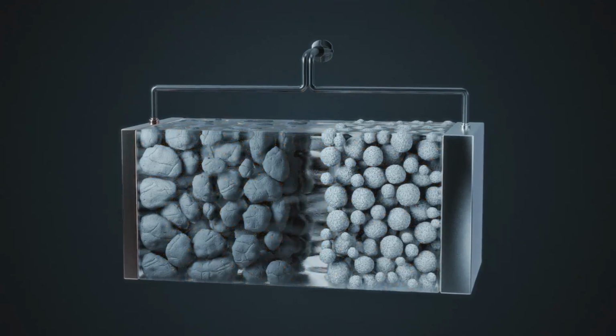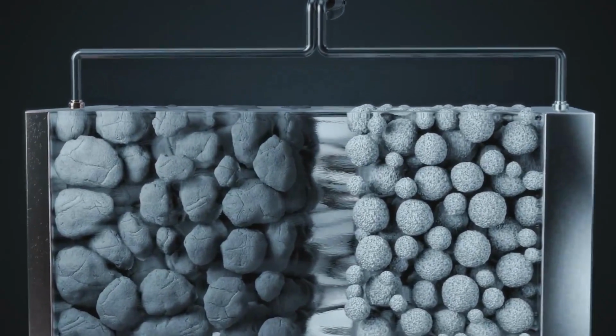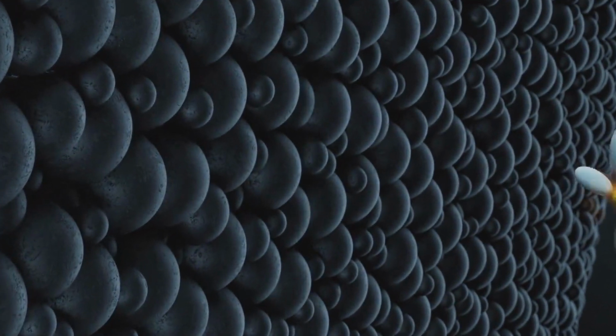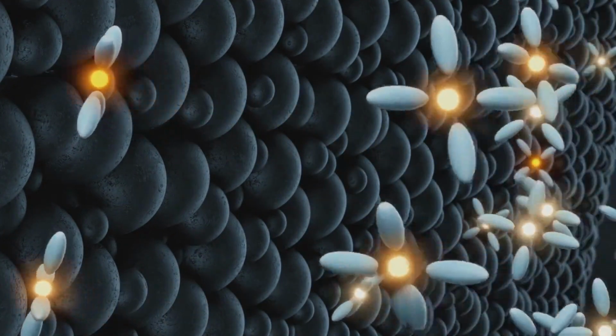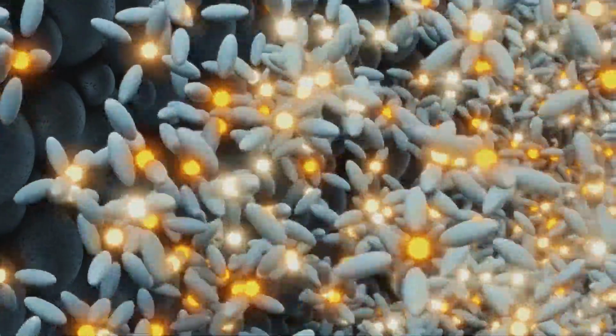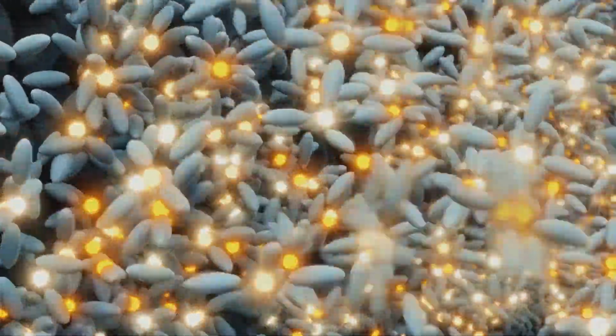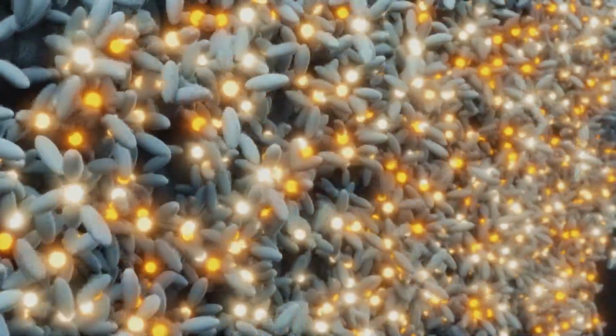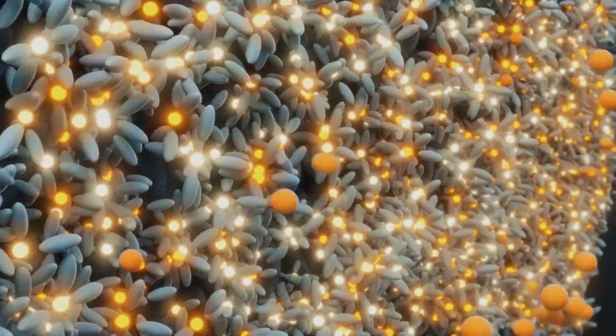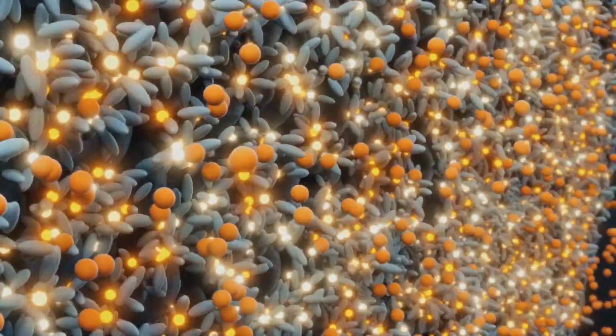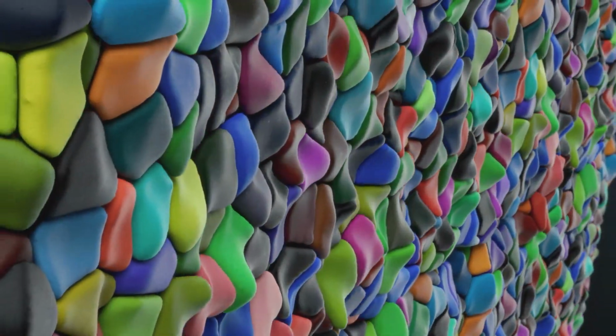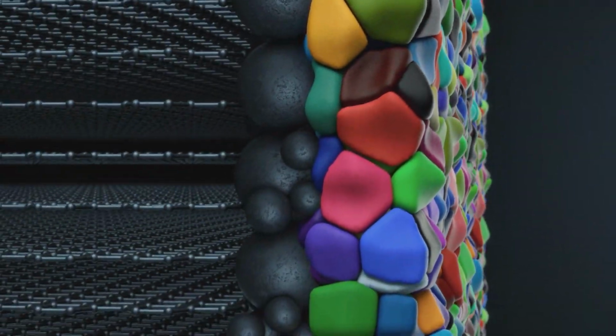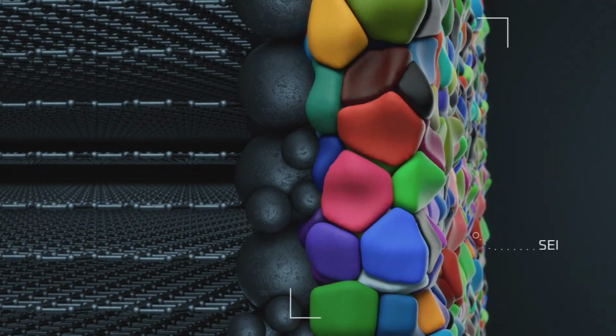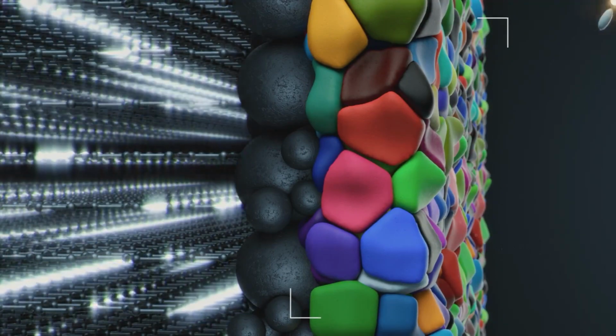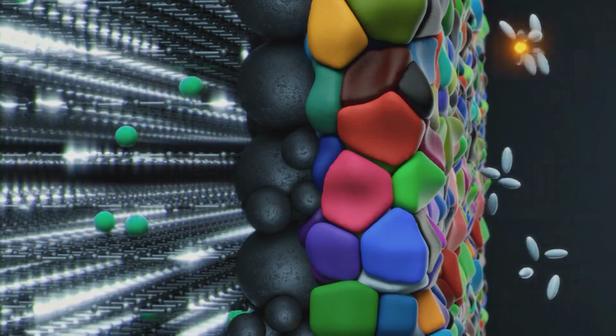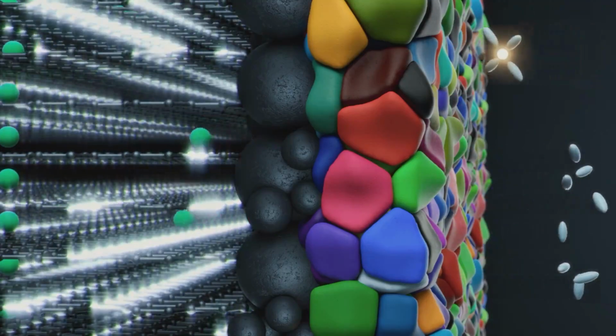In the meantime, there were several other mechanisms kicking into gear at the anode. Lithium, the solvent, and the additives are reacting with the shell of the graphite particles to form a protective film on the graphite particles. The vinylene carbonate additive helps this layer form into a stable surface that extends battery life to thousands of cycles. The layer is called a solid electrolyte interface. It's a solid-state layer that lithium ions will now pass through to enter the particles.